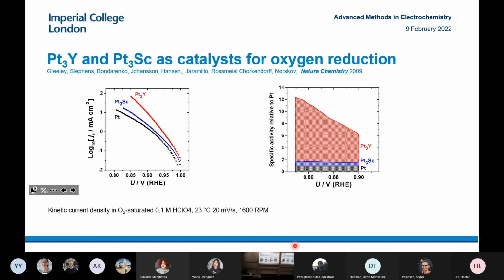We tested electrochemically. We've already shown this in my lecture on kinetics. It's important to show to all of you to make sure we're on the same page. And what we found is we saw up to an order of magnitude improvement, particularly in the platinum yttrium catalyst. The way we did this is important to mention. We took a 5 millimeter disc of the platinum alloy and measured it in a rotating disc electrode setup. So we sputter cleaned it to make it clean, and then we tested it.